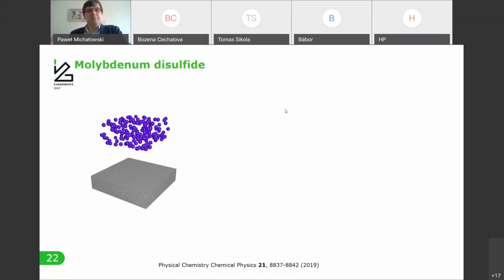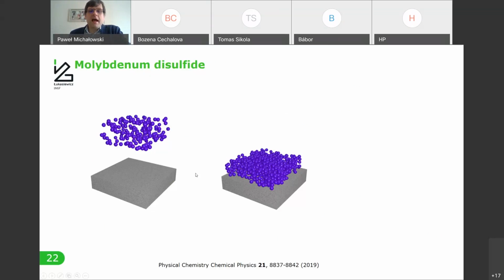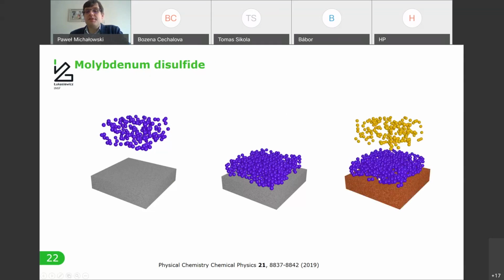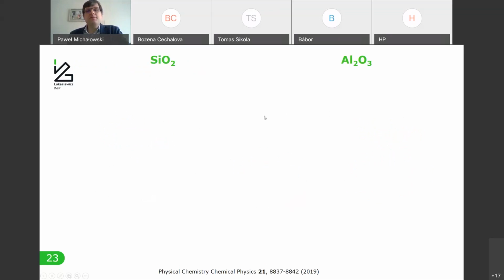So we made a simple process to grow 2D materials. Basically, first we deposited some molybdenum on a substrate. And then we use the high temperature sulfurization process to obtain the MoS2. Then SIMS revealed that there is a huge difference in quality of the materials depending on the type of a substrate we used.